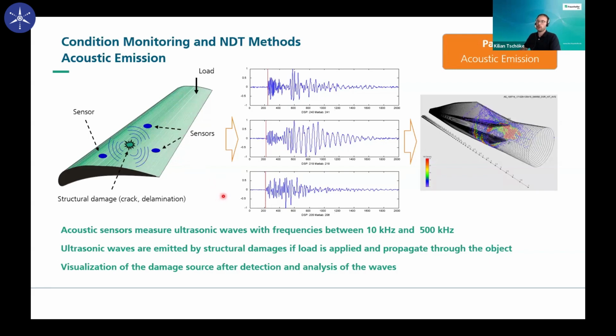And all these sensors are permanently listening to the structure. They are listening to acoustical events. An acoustical event, for example, could be a crack or a damage occurring in your structure. The crack, you can imagine, makes noise, makes a sound, makes an acoustical emission, an acoustical signal, and this signal propagates as acoustical waves in your structure, is measured by your sensor system, and then by analyzing the data, one can get information out of it.